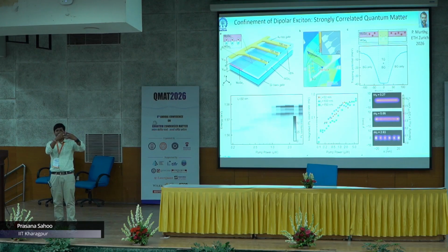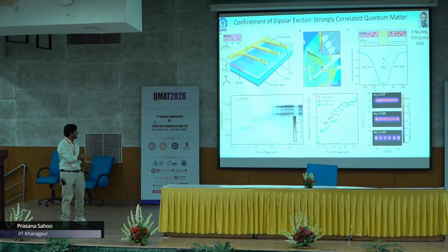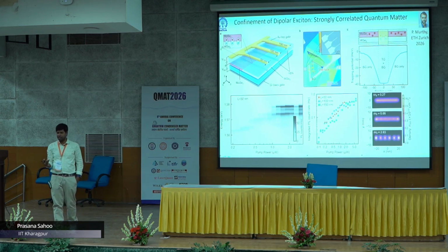Imagine you have the 5 exciton states. We expect that when we increase the power, all the states will fill equally, and eventually it will give a bright photoluminescence. But when you increase the power, this shifting is happening in the upward direction, and the higher energy states are saturating at a higher power. Again, eventually it is saturating. Usual PL is not saturated.